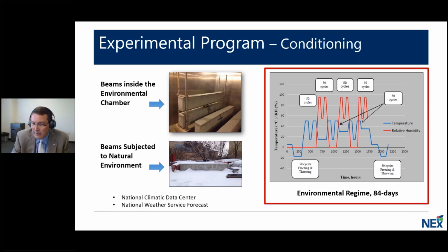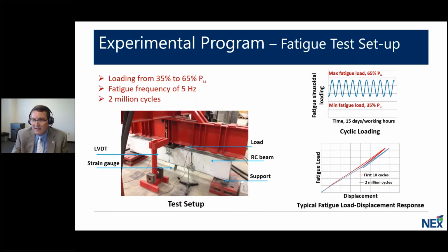Below, in the lower left-hand side, we also had beams that were placed in a natural environment that we currently have that we can do longer-term, multi-year tests on to evaluate. It's important to note those specimens are not under sustained stress, though. This slide shows the fatigue test setup and the fatigue cycling. The maximum load represents approximately the service level of the repair system that we would expect. And it may be noted that the level of stiffness loss is rather minimal, as shown at the bottom right, from the first 10 cycles to 2 million cycles.